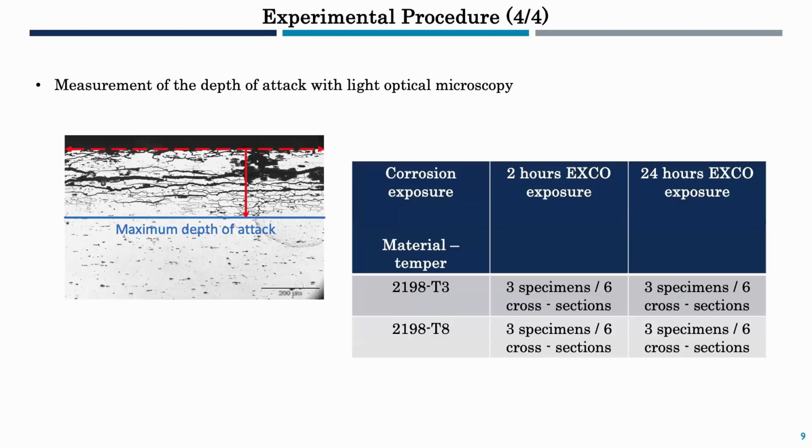In the microscope, we had several cuts, and we measured with a microscope the maximum depth of attack. And there I will show you the evolution of the crack depth versus different EXCO exposure times. We have selected in this publication a short one, 2 hours, and an excessive one, 24 hours.